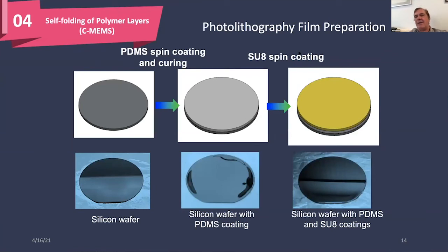So here, I'm repeating now the process, which is a little bit different from the previous one, where we were using droplets as actuators, so to speak. So we use PDMS now not as the active material, but as the support. And on it, we spin over SU8, and all of that is on a silicon wafer, right? And now we have a film that's really not attached to the PDMS at all. It can very easily come loose, but the solvent cannot go down, it can only go up.